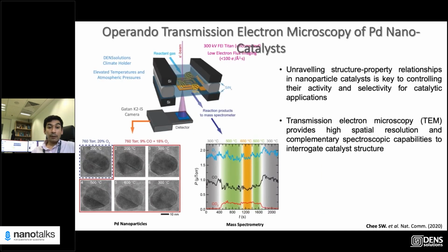And for that, we used a climate holder, and this was the first time we actually did the gas experiment, with palladium nanoparticles. Once I saw the movies, I was quite impressed. Even though you have 1 atmosphere pressure and a micron gap, you can't get to the desired resolution at these high pressures, but nevertheless you can really get the lattice resolution. You can start inferring what's going on structurally in these materials.